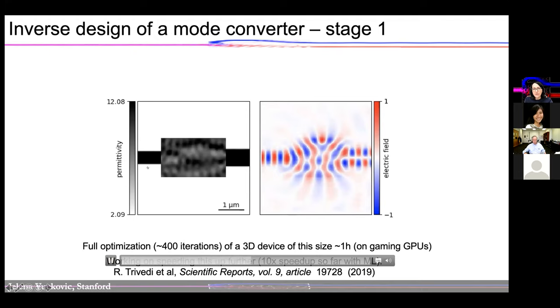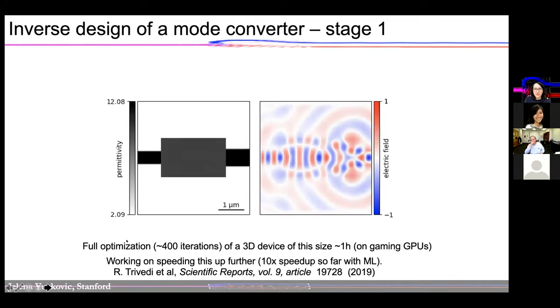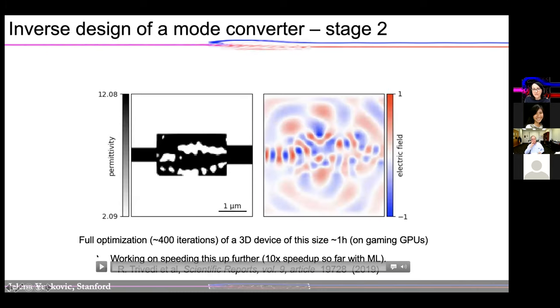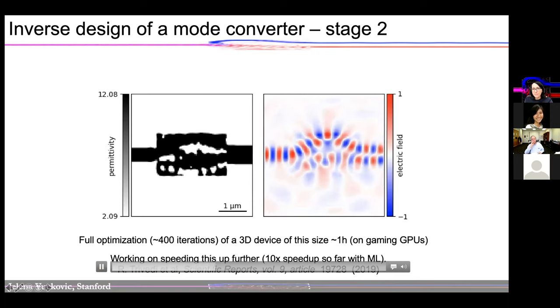So here we're converting first order mode to second order mode from input to output. And you see the design process and the corresponding electromagnetic field on the right hand side. So that's the first stage of optimization. The second stage of optimization, where you basically produce something that you can make binary, is optimization that incorporates fabrication constraints. So this is just kind of changing between refractive index of, in this case, silicon and air. And at the end, you stop when you reach target efficiency, which here was 90%, and you really map first to second order mode at the output.